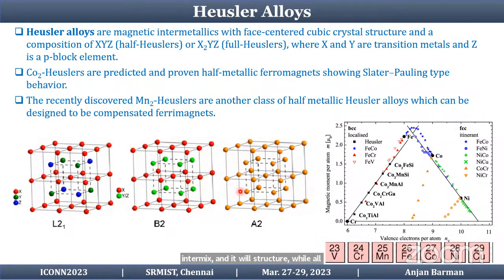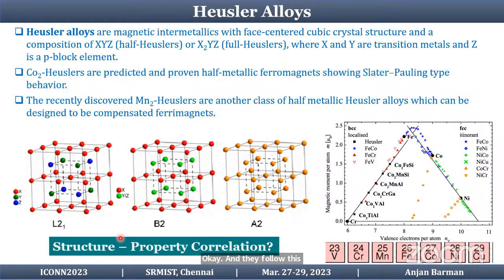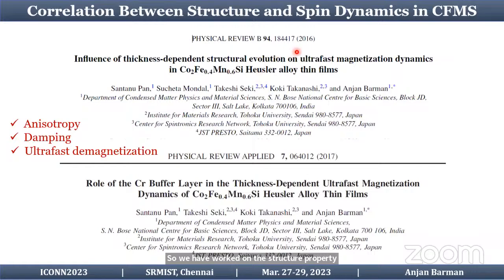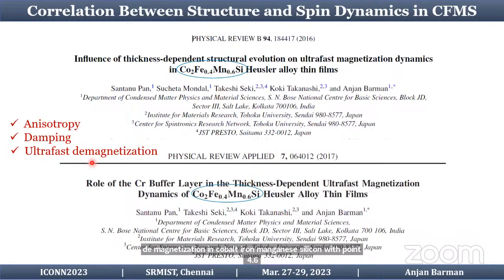So although the crystal structure is perfect, the chemical ordering goes from a perfectly ordered state to a completely disordered state, and they follow this Slater-Pauling type of behavior. So we have worked on the structure-property correlation in Heusler alloys in these two papers published in 2016 and 17, where we have shown that the anisotropy, damping and ultrafast demagnetization in cobalt, iron, manganese, silicon with 0.4, 0.6 composition in both cases can give rise to all these properties, and there is a structure-property correlation.